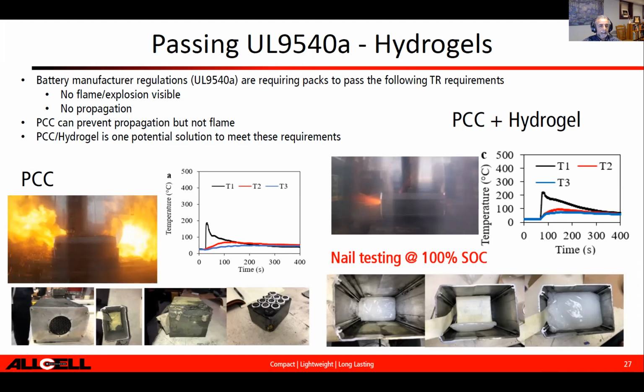And the industry is handling that in the way that we see that's going to be very common is what's the UL recommendation is a new regulation that's called UL 9540A. And what is that said? Basically, for a pack to be safe, you have to do two things. First, you have to prevent the propagation of the cells from one cell to the other in the pack. And the other one, you have to prevent the flame from coming out of the pack itself. We have done testing on this similar packs that we have developed at AllCell, and as you can see, the one to the left, that even if you manage to stop the propagation, you still have that flame coming out of the cell from a single cell, and that is something that is significant.